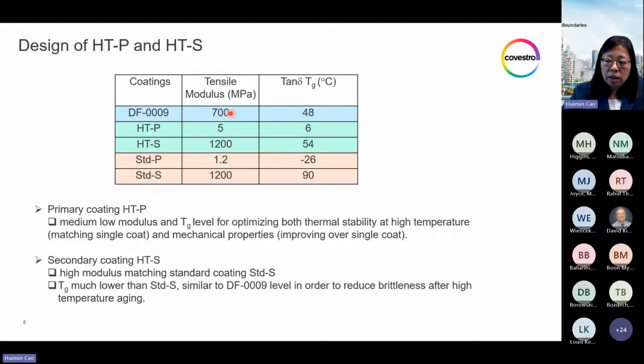To improve the microbending performance, the secondary coating is designed at the same modulus level as a regular secondary, but with a Tg lower than the regular secondary coating, more similar to the single coat. And this is to avoid the embrittlement after aging.